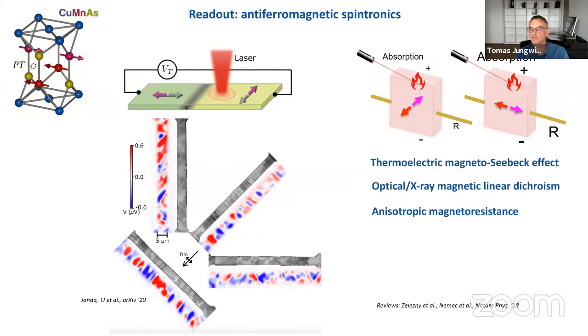Now, we had the electrical version of the anisotropic magnetoresistance. We have the optical counterpart, or linear dichroism, but you can also have a thermoelectric counterpart, which is called the magneto-Seebeck effect. So now instead of applying electrical bias, you can apply a thermal gradient, and in response, you will measure electrical voltage, and now this electrical voltage will depend on the orientation of the spins or the Néel vector. The nice thing about this probe is that you can use focused laser beams to induce local heating and then measure the thermal voltage response to that.